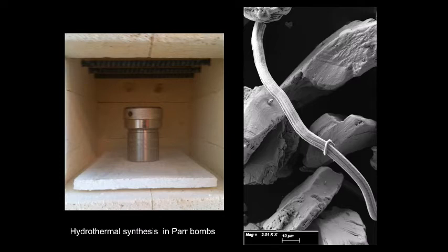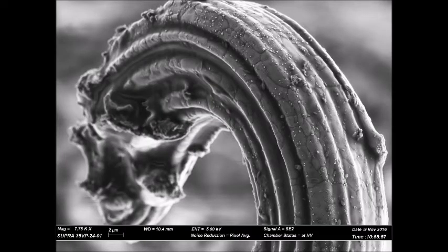And this is a SEM image of an example of a wire that has been grown hydrothermally in the laboratory. Now, based on all of the experiments that we've done, hydrothermal, in the flame, and in the scanning electron microscope, and analysis of the resulting samples, we have a model and a much better understanding for how these wire silvers are growing. First of all, the texture of the wire silver, which previously had not been fully understood, is comprised of multiple small single crystals over which the striations are superimposed.